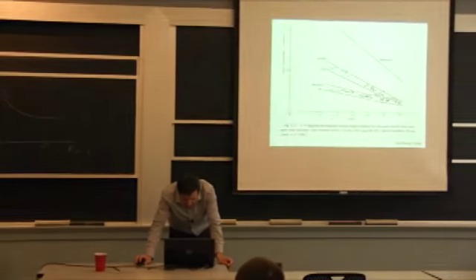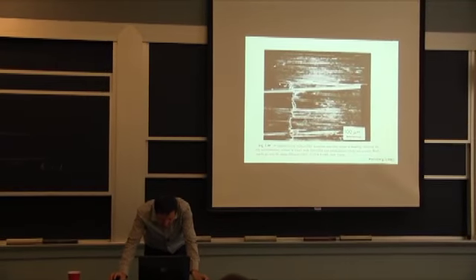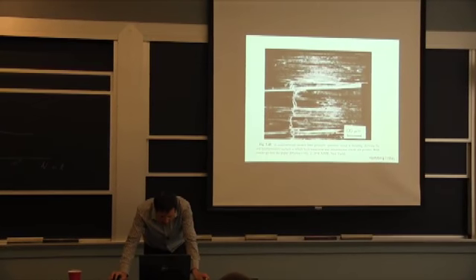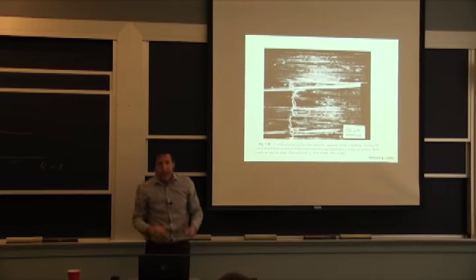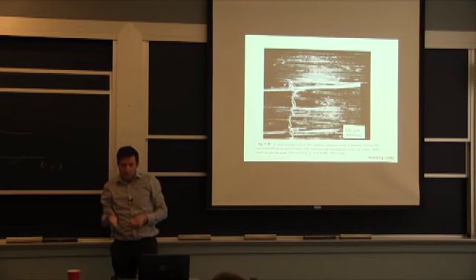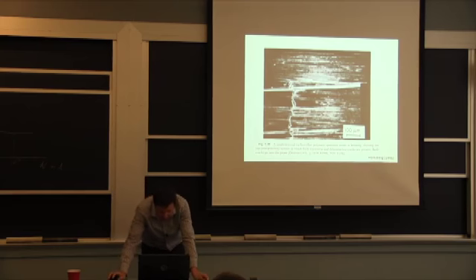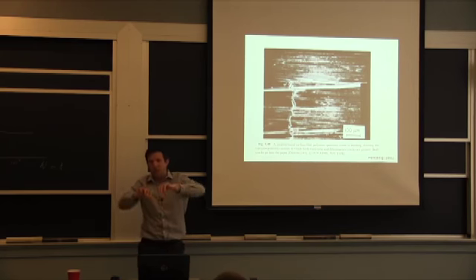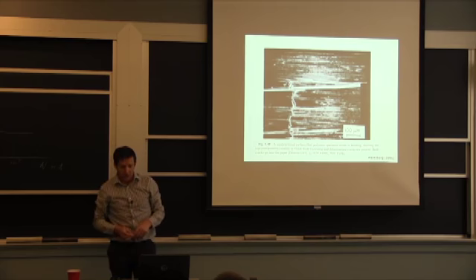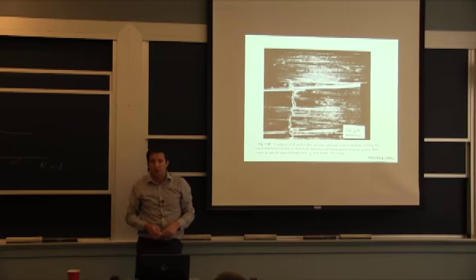Then you crack, and I have an image here where eventually the crack will have to go between fibers. So if they're not continuous, that's a preferential site. But you can see how jagged the crack is in this case. This was a bending experiment. It started cracking here, went through about half of the thickness and then started to transition in shear. The nominal tension stress was going down as you keep going through the material, and eventually you have more of a delamination fracture. So it didn't go really through the thickness.